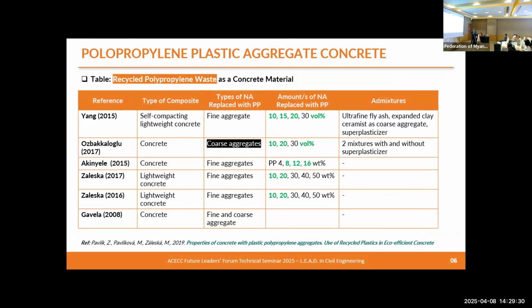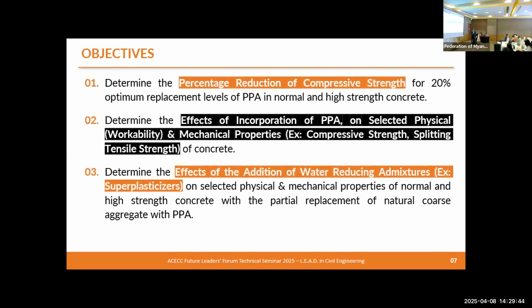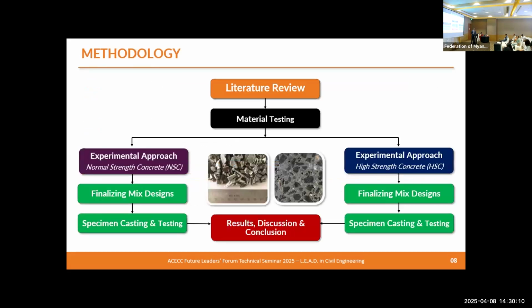You can clearly see that it's mostly used as a replacement for fine aggregate sand, and the optimum replacement levels are around 20%. And most of the studies have been conducted only for normal strength concrete. So these are our objectives: determining the percentage reduction in compressive strength with this incorporation, determining both physical and mechanical properties, and finding the effects of admixtures, because nowadays most concrete is produced with admixtures to get better quality. So we thought of examining that as well.